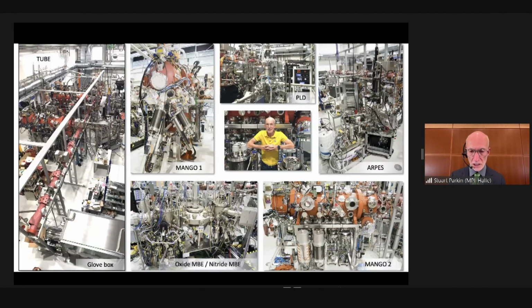And this is possible using simple techniques, a technique called sputter deposition. And this is something that I used on the very first spin valve sensing devices. And I'm just showing you here an image picture of the system that I built in my new institute in Germany. And on the left-hand side, you can see a tube. This is in orange. It's 15 meters long. It's an ultra-high vacuum tube in which we've designed and built robotic systems that enable us to automatically transfer by computer control a substrate, a wafer, onto which we will deposit the atomically thin layers.